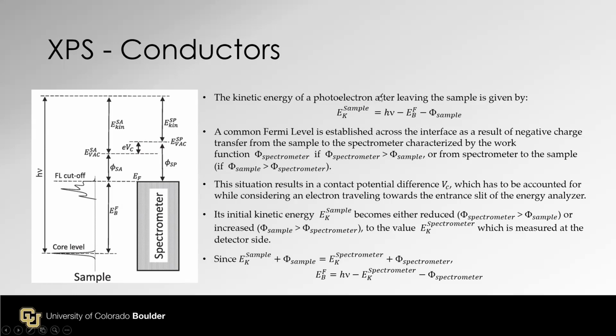Starting equation is same as the one in the previous screen. Kinetic energy of the sample equals to that. Okay. For that, if your sample is conductor and it is mounted in the conductive fashion, the common Fermi level between your sample and the spectrometer should be established across the interface.